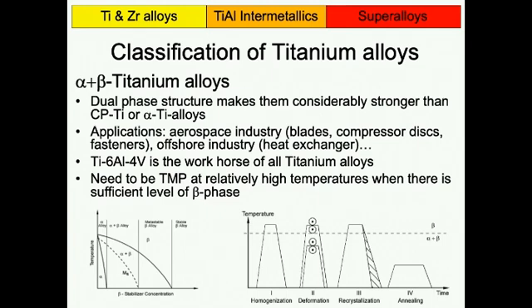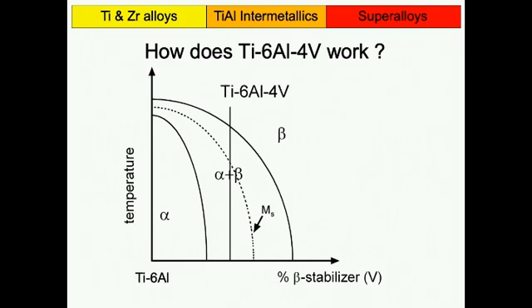These alloys are too strong to be processed at room temperature. You can't roll them or anything at room temperature. So they are thermomechanically processed, and they're actually processed at relatively high temperatures. What that actually means is they are processed when you have relatively high amounts of beta phase. And you can see that here, but I actually have another graph here, schematic. And this is really quite important for you to understand.